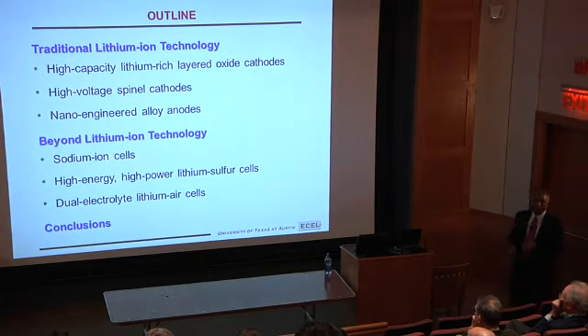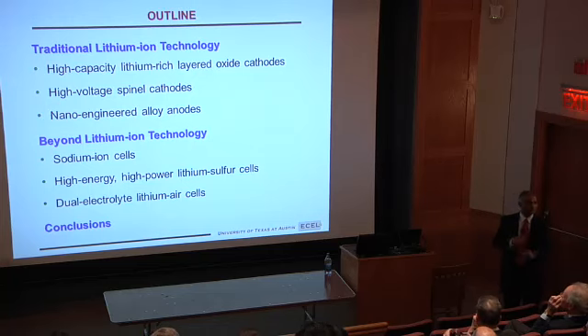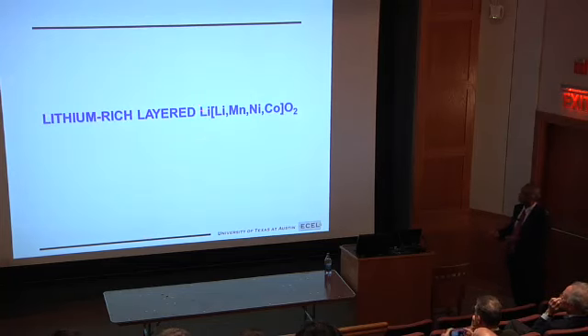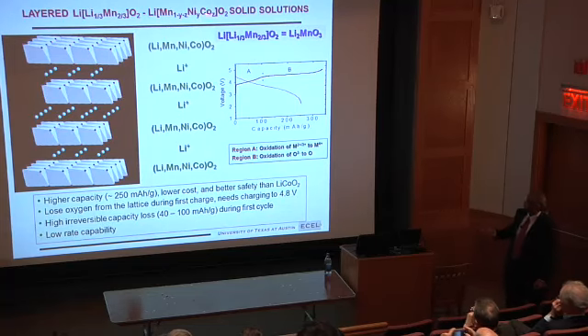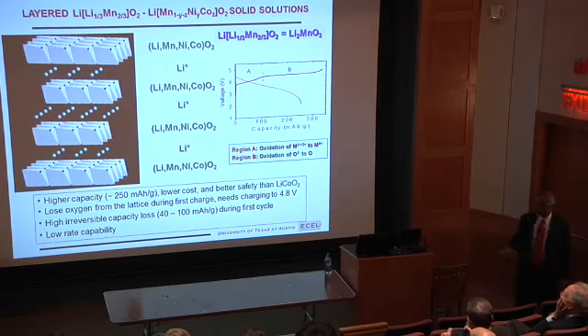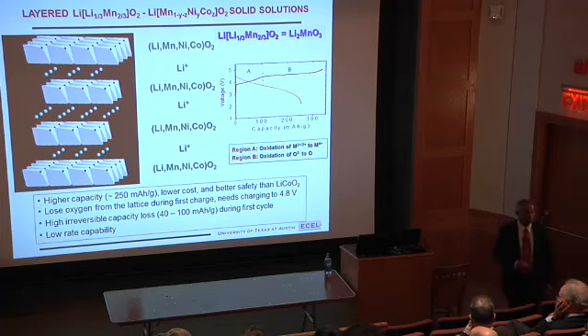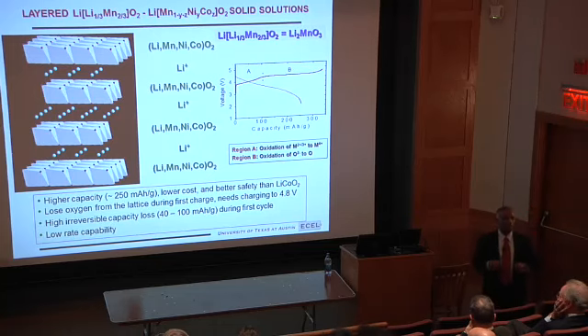Now, this is my list, and I don't think I can go through everything, so let me tell you first, lithium-rich layered. This is a material patented by Argonne and licensed to a lot of different companies I mentioned. Right now, the technology is based on approximately 150 or 160 milliamp hour per gram, less than 200 milliamp hour per gram. That's all we have right now. This material, 250 to 300 milliamp hour per gram. That's why everybody is interested, and a lot of people have licensed this material.